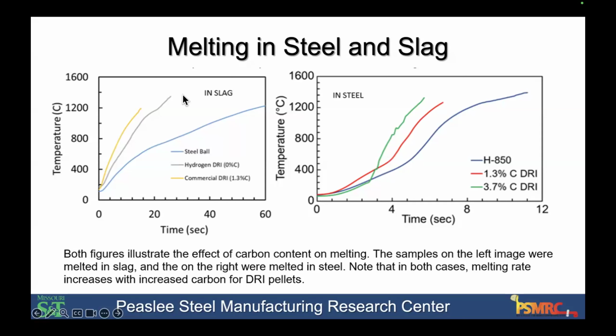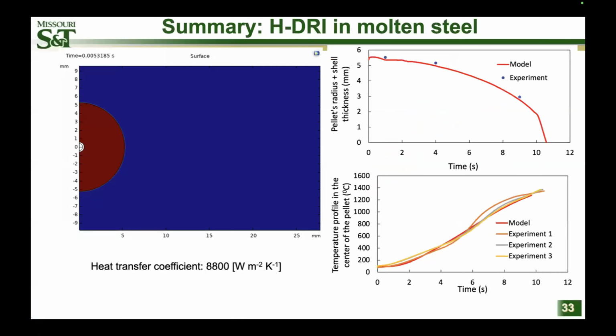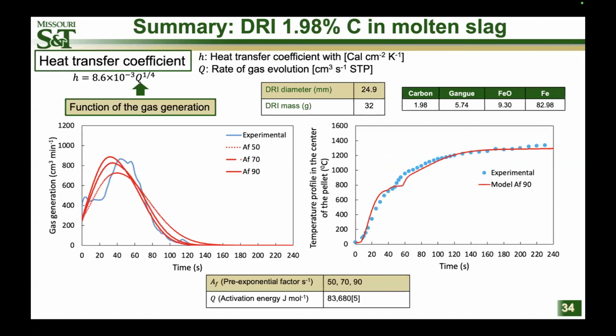We also have done these types of measurements in steel and slag systems, since the melting of DRI can occur in steel, in slag, or at the melt-metal interface. So these models have been developed to predict the melting behavior, and we then use those in larger scale models to characterize the melting characteristics of these materials.